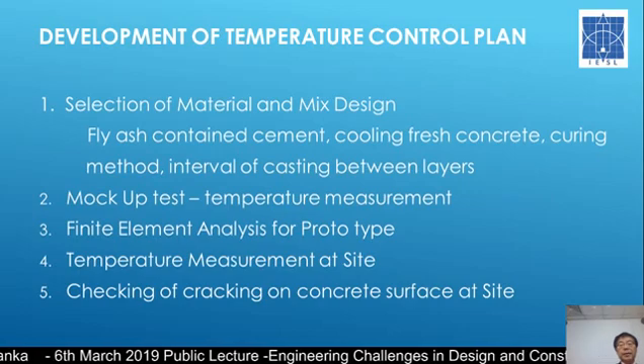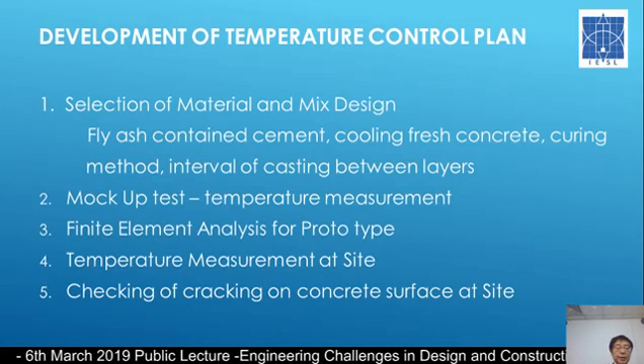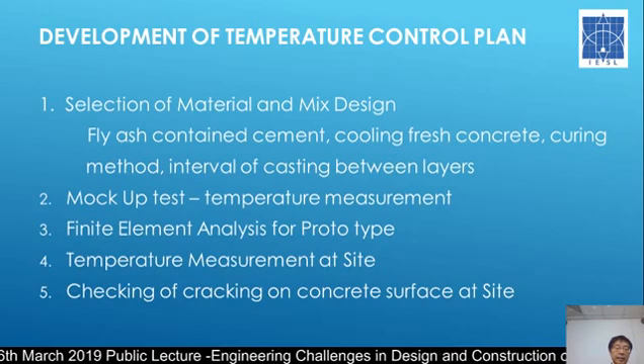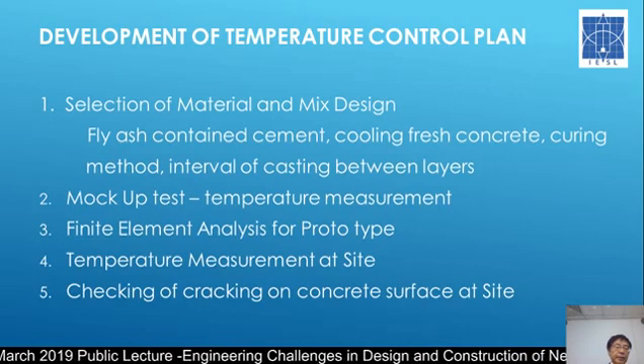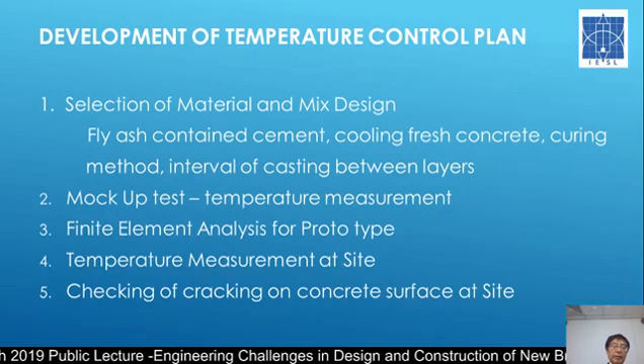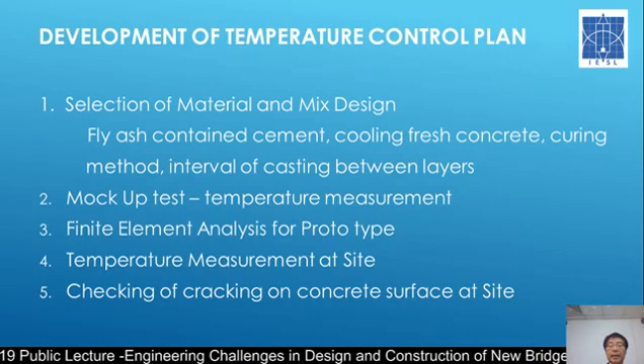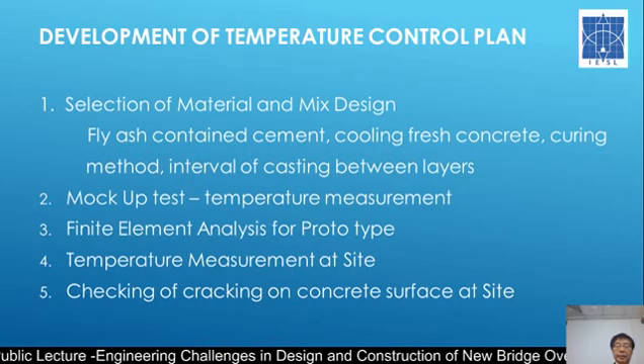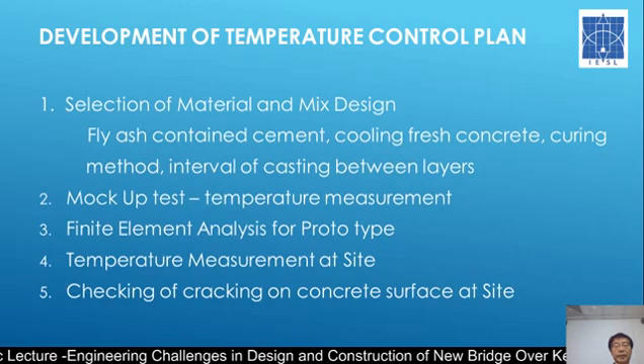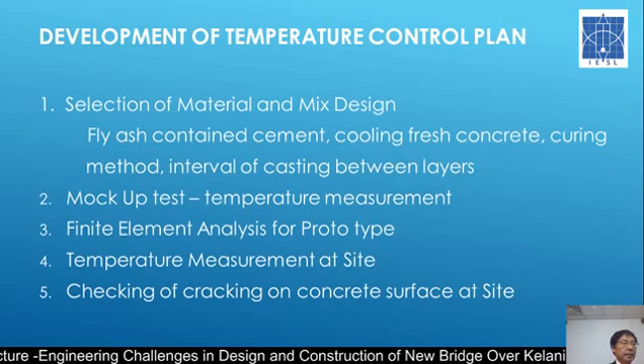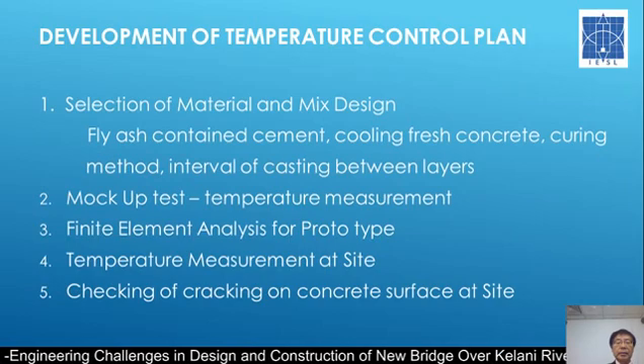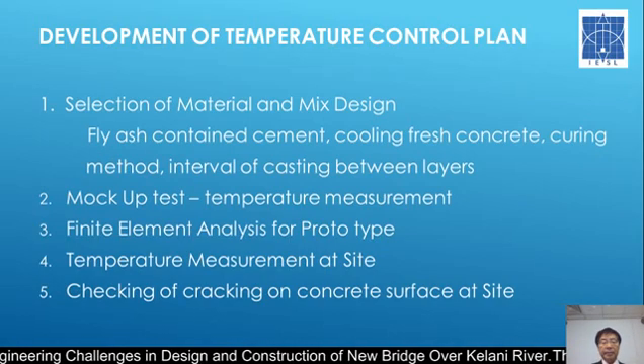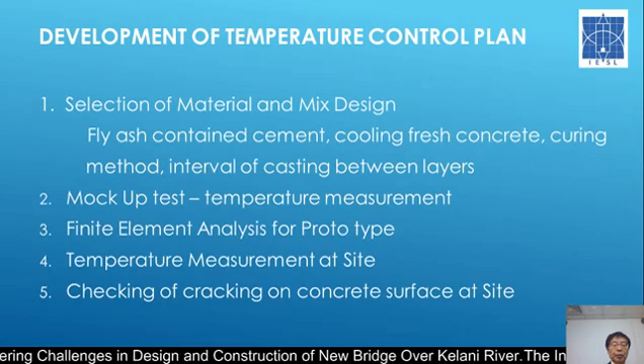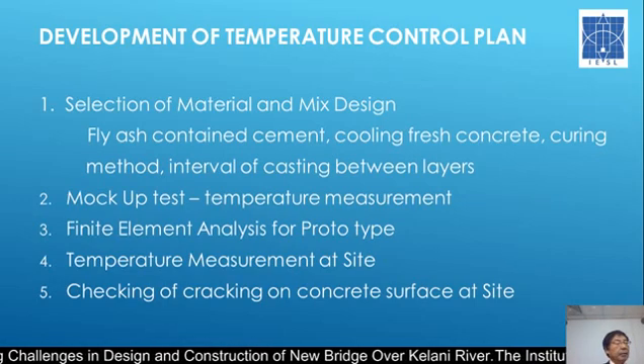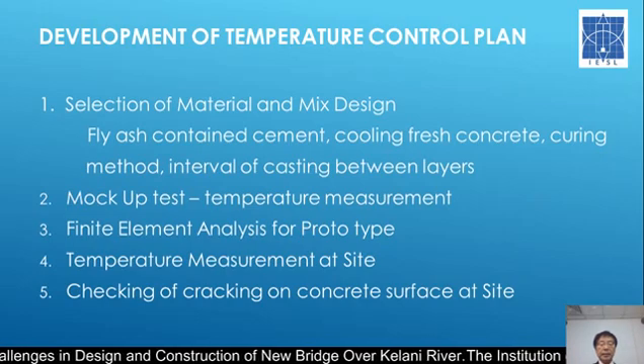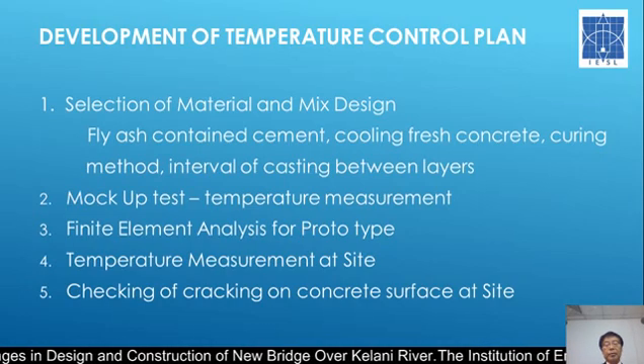So in order to control the temperature, what we have to do first is the selection of material and the mix design. Fly ash is very helpful to reduce the temperature, so cement containing fly ash is very useful. And cooling the fresh concrete itself, by adding some ice into the mixing water, or cooling water circulating in the mass concrete. Curing method is also very important. In addition, the interval of casting between layers is also a parameter to control the temperature.